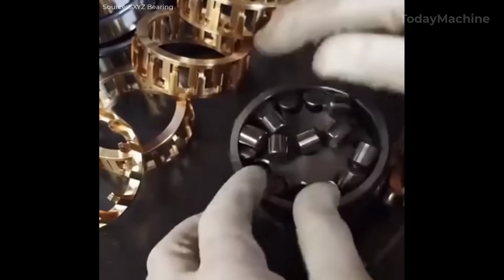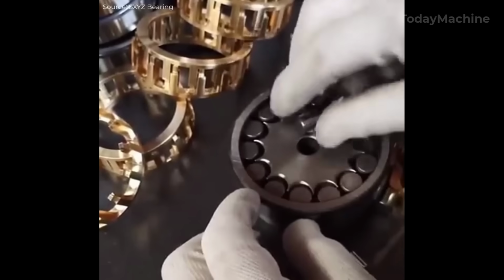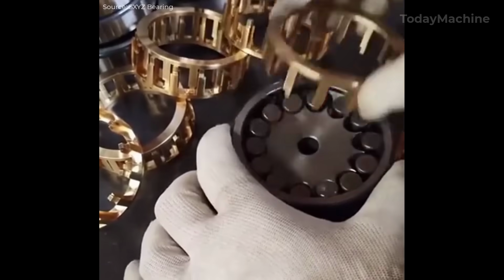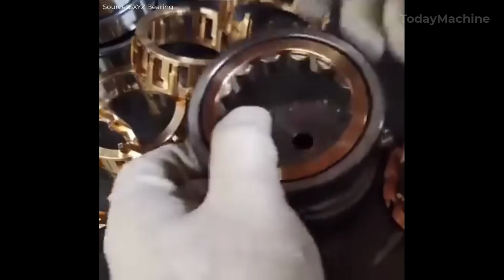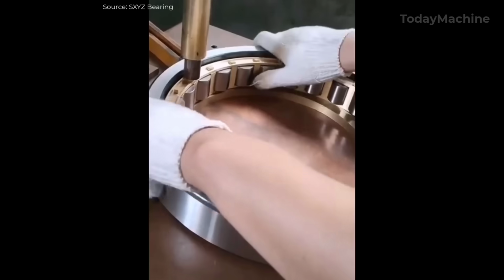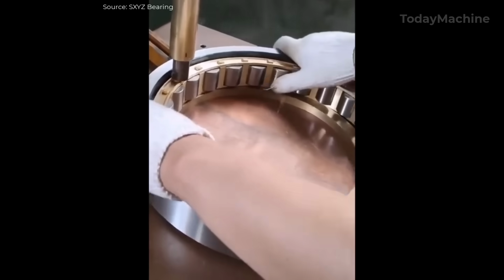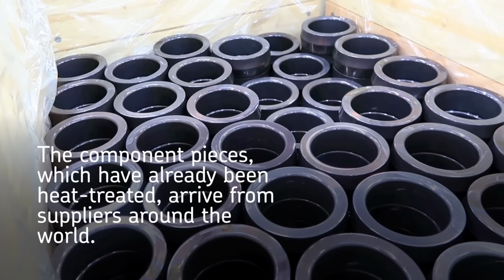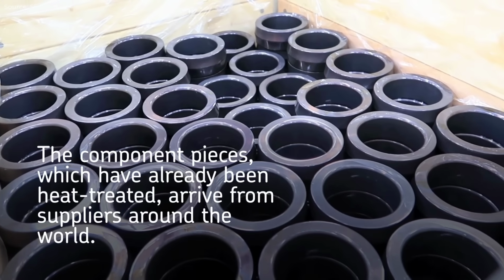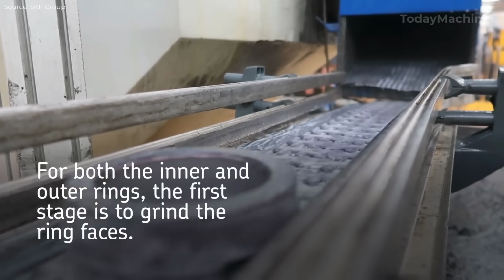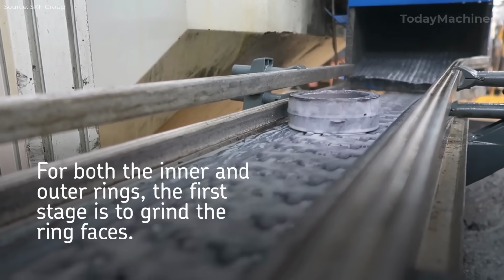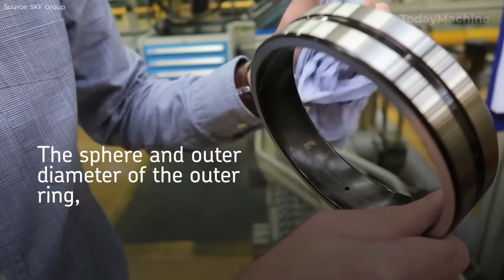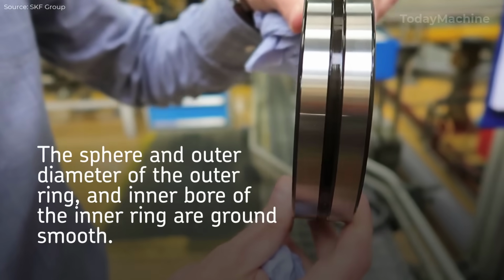SKF spherical roller bearings are manufactured with precision and quality, even today, at the SKF Luton facility, which produces approximately 3 million spherical roller bearings annually. The manufacturing process begins with the arrival of heat-treated component pieces, including the inner and outer rings, sourced from suppliers around the world. The first step in production is grinding the faces of both the inner and outer rings to ensure they are flat and parallel. The outer diameter of the outer ring, the sphere, and the inner bore of the inner ring are then ground to achieve a smooth finish. Following this, the inner ring raceway is ground and honed to meet specific surface characteristics, which are critical for the bearing's performance.